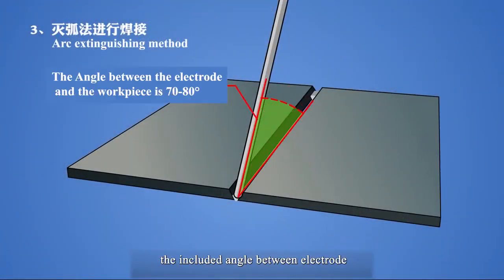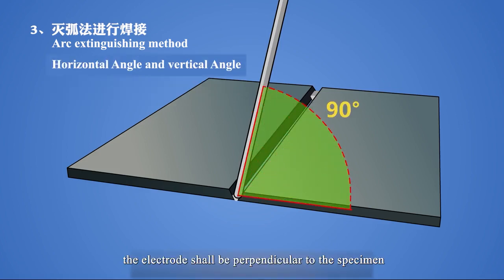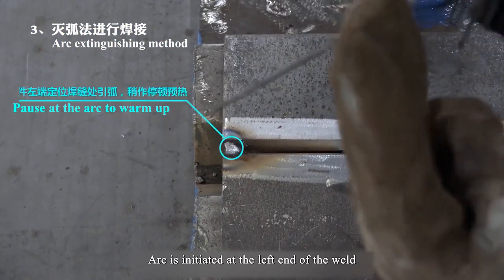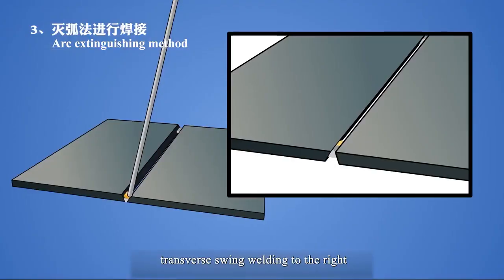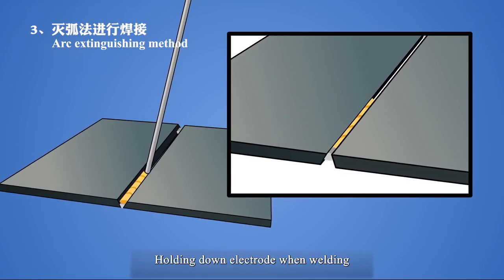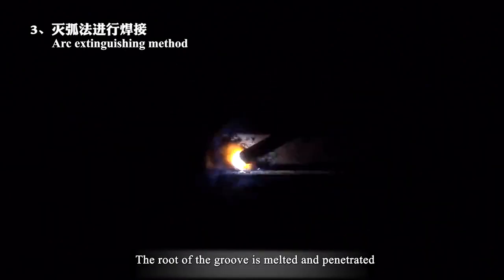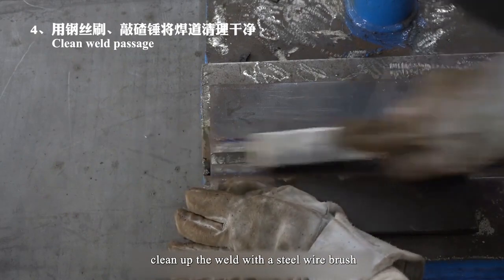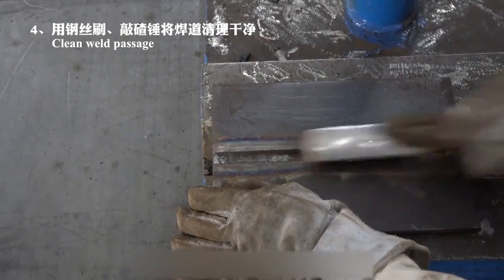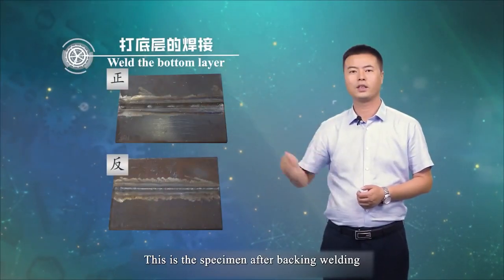When welding, the included angle between electrode and welding direction is 70 to 80 degrees. Meanwhile, the electrode shall be perpendicular to the specimen on both sides. Arc is initiated at the left end of the weld, carried up, transverse swing welding to the right, holding down electrode when welding to the right edge of the positioning weld. The root of the groove is melted and penetrated. The arc is closed after the molten hole is formed. The arc extinguishing frequency is 50 to 60 times per minute. After the backing welding, clean up the weld with a steel wire brush and the slag hammer. This is the specimen after backing welding.